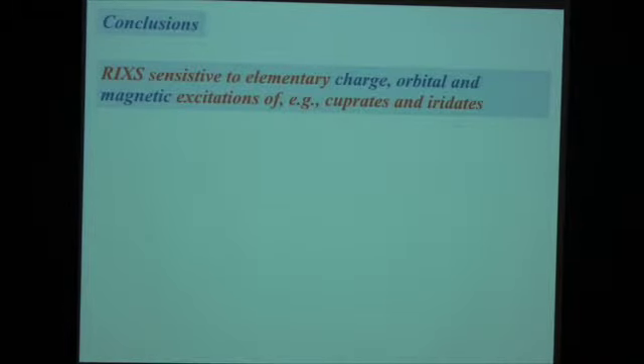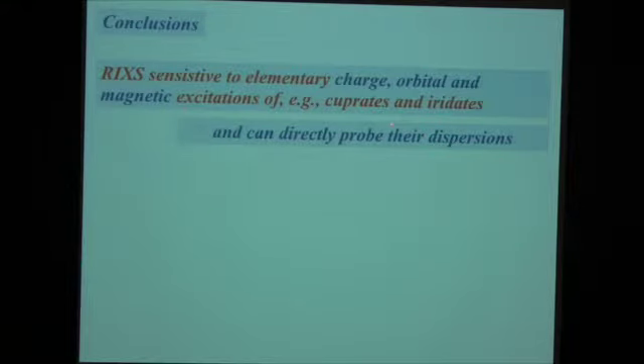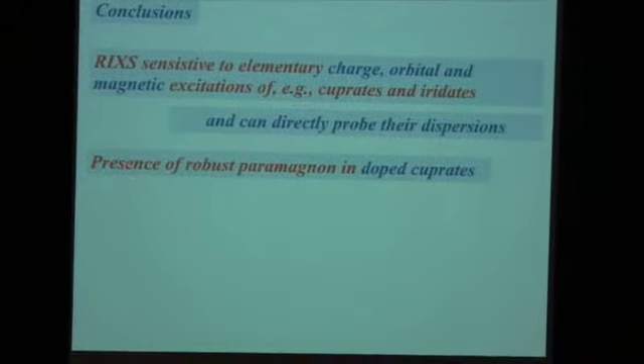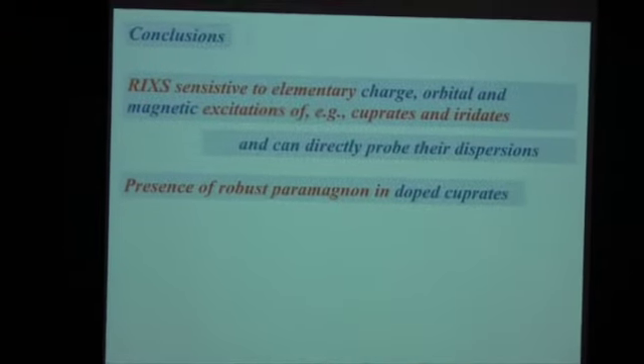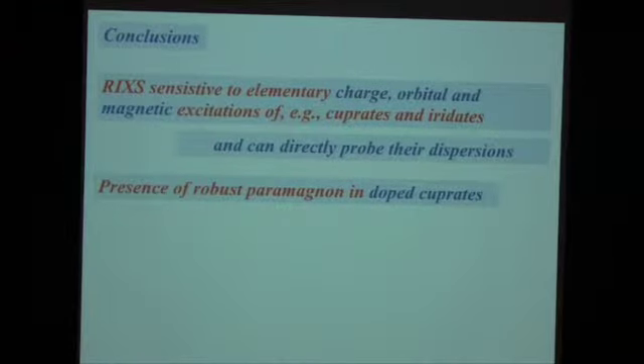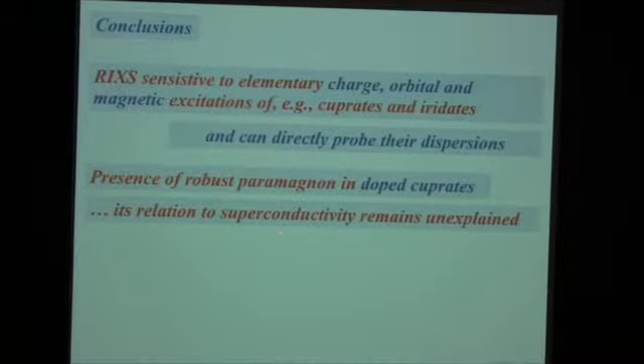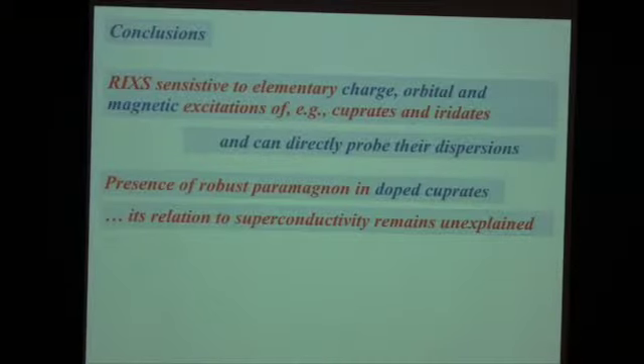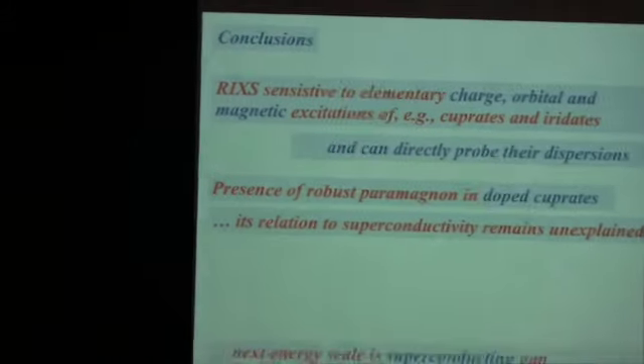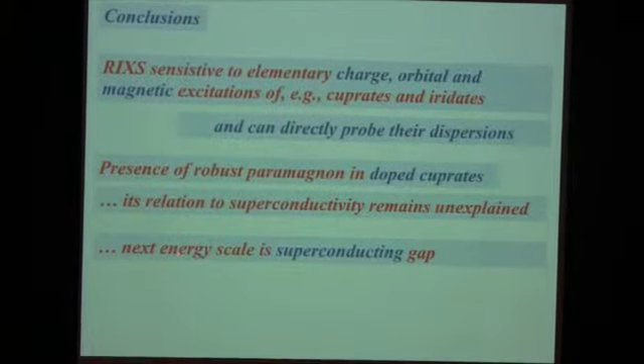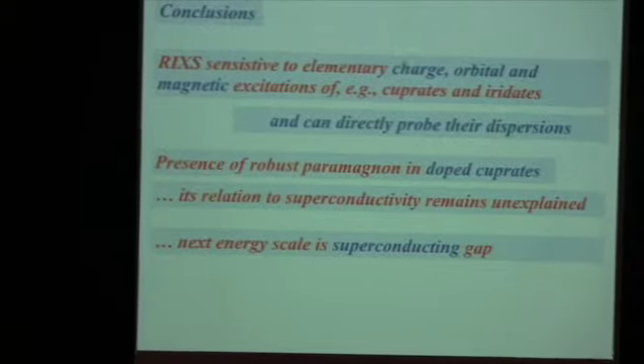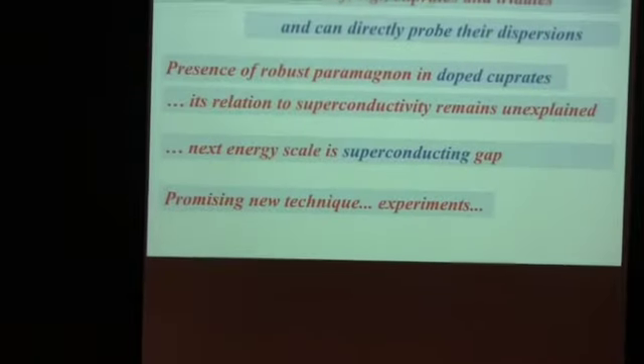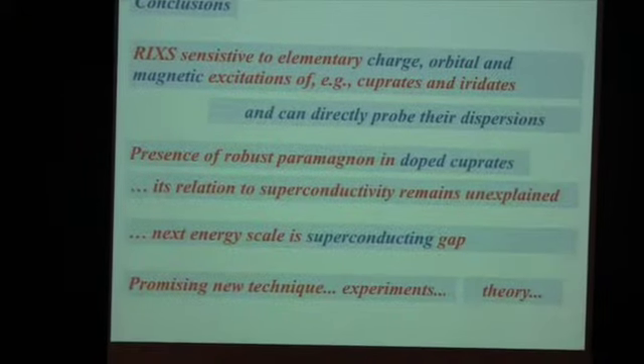Conclusion is that RIXS is sensitive to elementary charge, orbital and magnetic excitations of, for instance, cuprates and also of iridates. It can directly probe the dispersion of these orbital and magnetic excitations and also charge excitations, although I didn't show that today. There is experimental evidence of a robust paramagnon in the doped cuprates, or low energy excitation on the magnon scale in the doped cuprates. Its relation to superconductivity remains to be explained. Its origin, in my opinion, remains to be fully explained. And the next energy scale that, of course, RIXS wants to look at is the energy scale of the superconducting gap, but we are not quite there yet. I hope this promising new technique will give rise to new experiments and hopefully also some new theory along the way. Thank you for your attention.